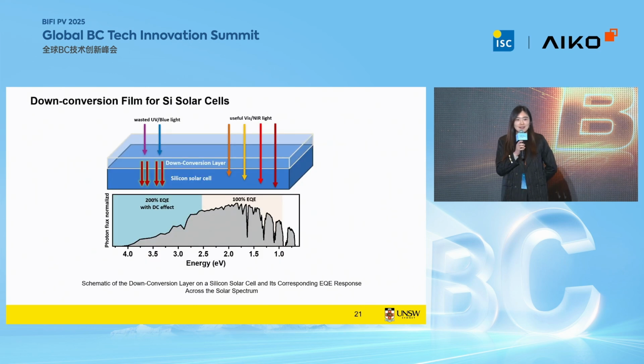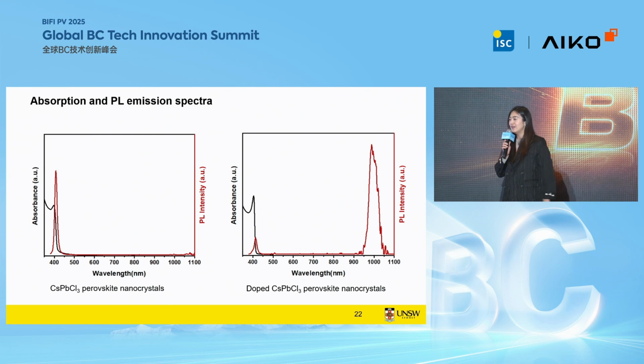Okay, so as I said, we are doing this downshifting for a bit of near-term impact, and for the long term, we are not satisfied with only 100% PLQY. We want to further push it to 200%. So that's why there's the concept of down conversion, where you can convert one incoming high energy photon into multiple lower energy photons. And theoretically, the PLQY can achieve 200%. And this is what we've been doing in our lab. So again, using the nanoparticles as an example.